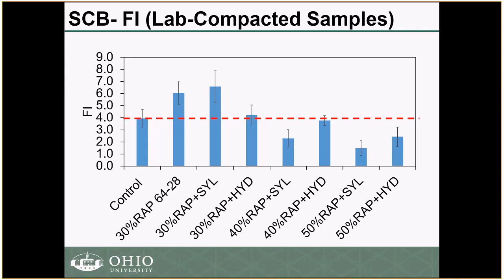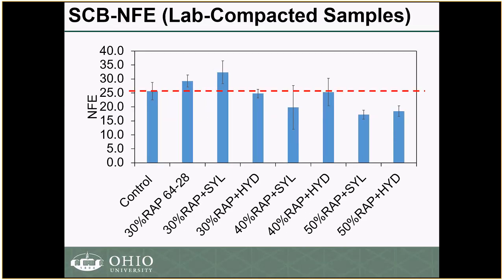If we look at the lab compacted samples, which are field produced and lab compacted, we're seeing a similar trend as the cores, but the main difference is that the lab results had lower values. Other studies have reported that this might be attributed to different things. The first is that lab compaction will not be the same as field compaction. And although we corrected for thickness, there was still a difference in thickness between the samples. In terms of the normalized fracture energy, we noticed similar results.